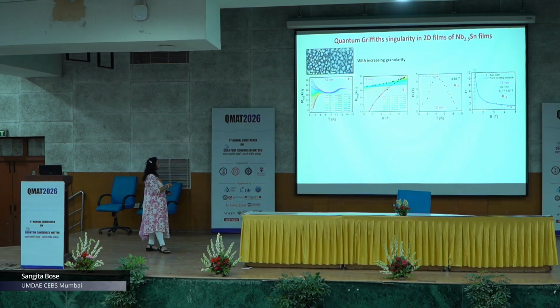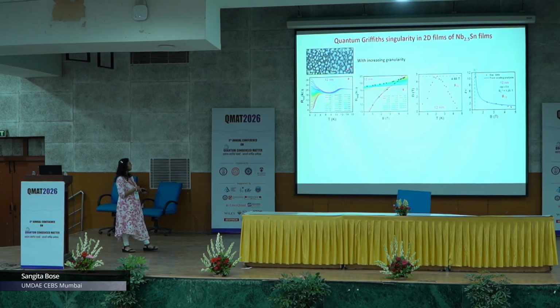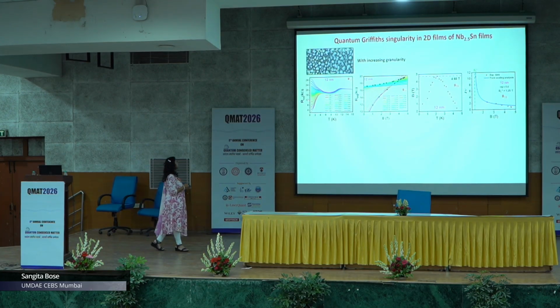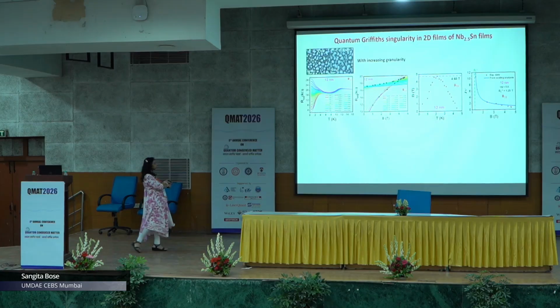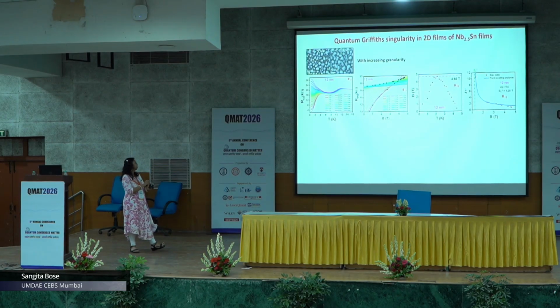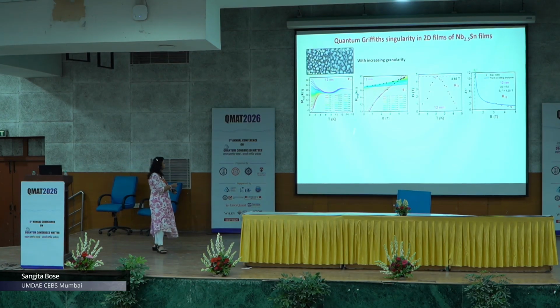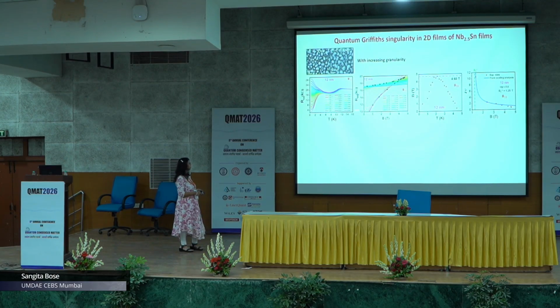We did it with increasing granularity. So, we reduced the film thickness. I have already told you before that as you reduce the film thickness, you make the systems more granular, our intergranular regions increase, and this is the result which I am showing you for a 12 nanometer film. Remember, previously I was showing that for a 13 nanometer film, for the parallel magnetic field orientation, we were not observing any kind of magnetic field driven phase transition, but in the perpendicular orientation we do see this.